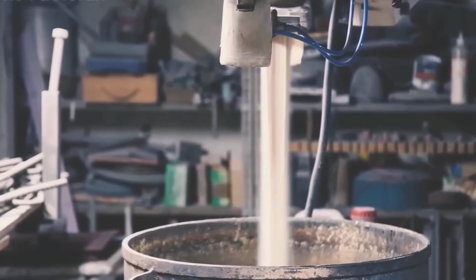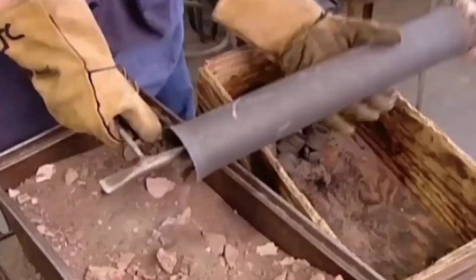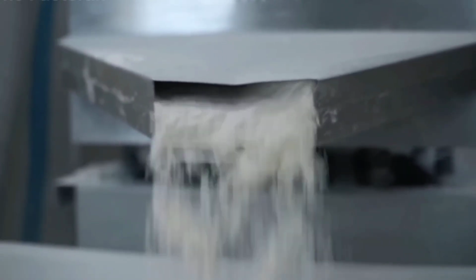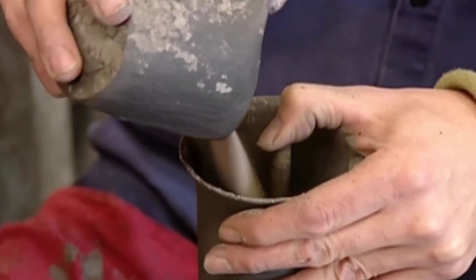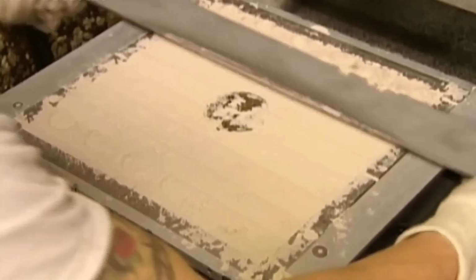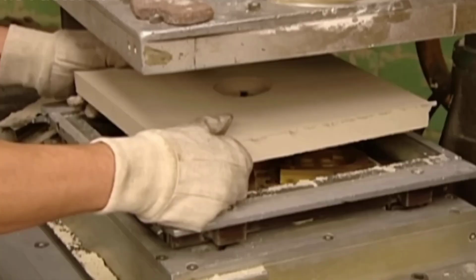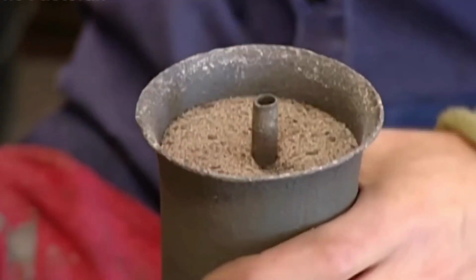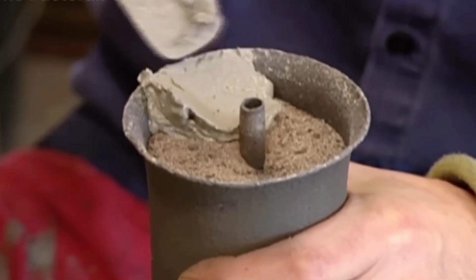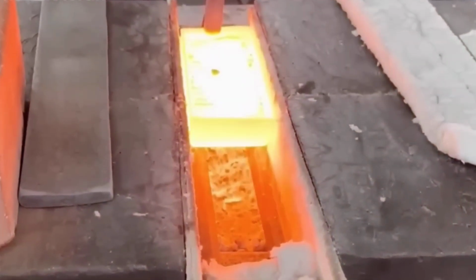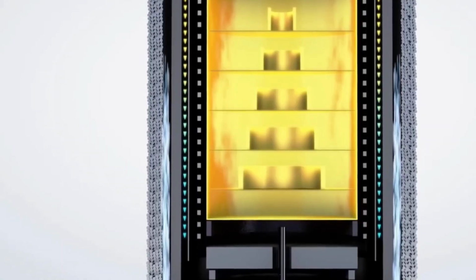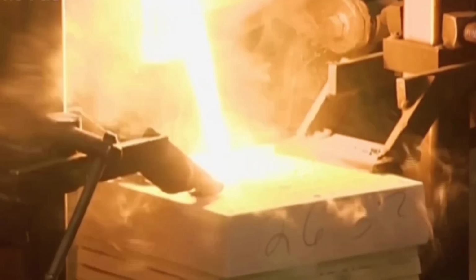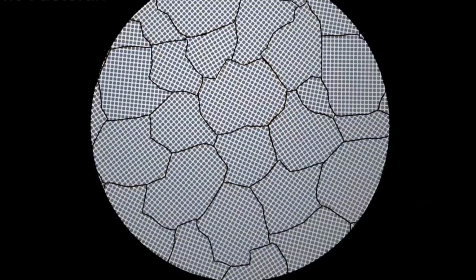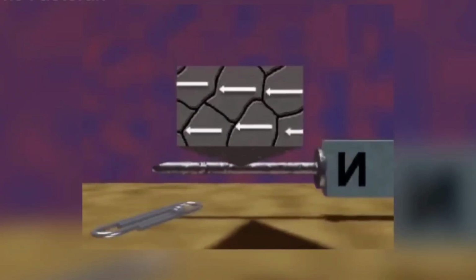After the neodymium, iron, and boron alloy has been refined, it is ground into an ultrafine powder inside an inert gas environment to prevent oxidation. The resulting mixture appears dark gray with a subtle violet tint, and its particles measure only a few microns across. This magnetic powder is then placed into a high-pressure steel mold while being exposed to a powerful magnetic field reaching several Teslas. Within this field, millions of microscopic alloy particles begin to rotate and align in the same magnetic direction, much like countless compass needles all pointing toward a single pole.